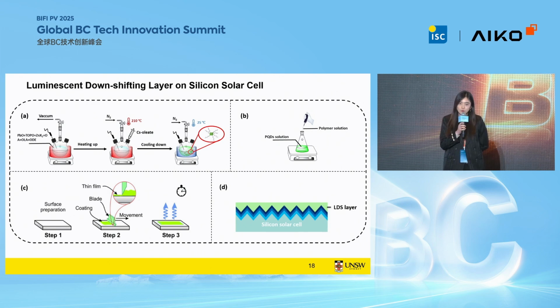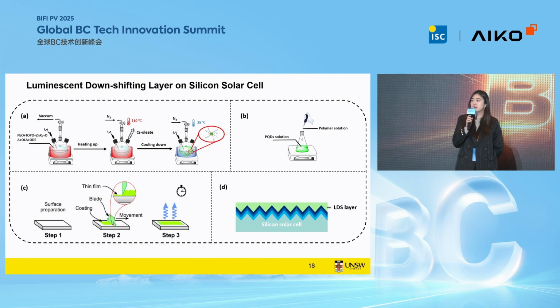And here's what we've been doing in our lab. We are testing different materials. Here's just one example where we are using nanoparticles. We use the hot injection method to synthesize our nanoparticles and then mix them with commercial polymer materials like EVA or POE, and then use the Dr. Blade method to apply them to our devices. And you will form these amazing downshifting layers. And we can see efficiency enhancements of between 1% to 2%, relatively.